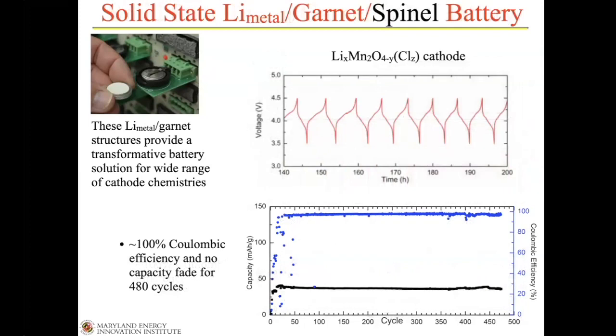We later on tried some high voltage spinels. These are 4.5 volt spinels. And you can see now much more stable data. This is 480 cycles. Again, great coulombic efficiency and no capacity fade for 480 cycles.